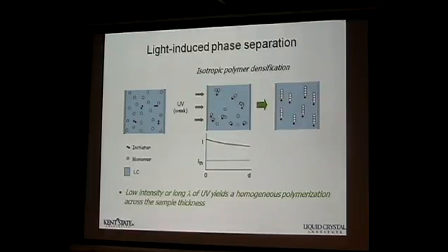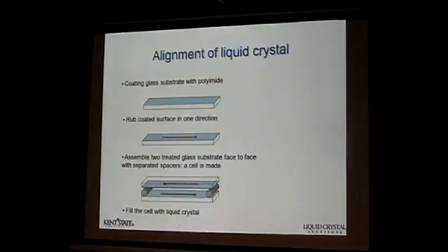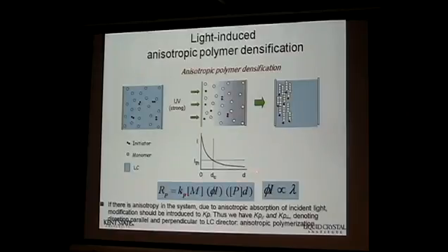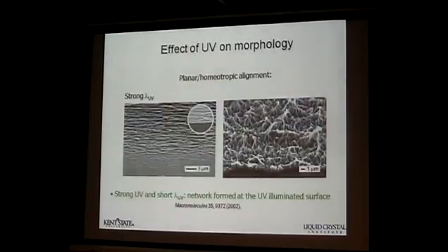But let's go back to the previous slide. You see in the previous slides that this is the threshold of light intensity, right? But this threshold of light intensity is only within a certain distance of the front substrate, right? Only within this, maybe 1/10, 1/5 of this light intensity, and now it works. So you see that in the majority of the cells, the light intensity falls underneath the threshold required for the chemical reaction to happen. So that's kind of the process.